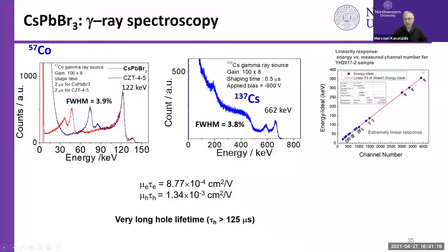And again, you see a very linear response between the energy of the gamma ray from different elements and what we see as the photopeak here. We can calculate the mu tau products, which are close to 10 to the minus 4 for electrons, and for holes slightly higher, 10 to the minus 3.